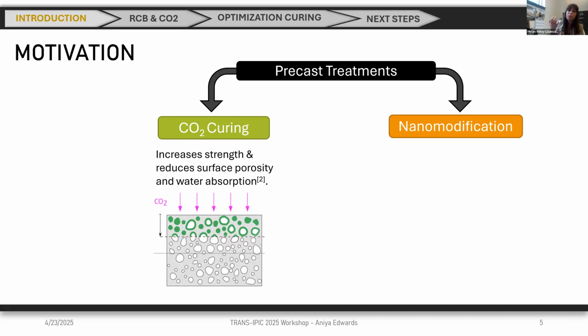What happens is CO2 penetrates the pores, and especially in the first layer, the CO2 will carbonate belite, and some calcium hydroxide if there is already some formed, and so forth. And because calcium carbonate occupies more space than calcium hydroxide, you will have a reduction in the porosity.